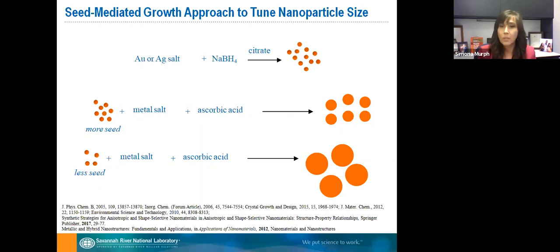And you can see here what I display. They are actually spherical nanoparticles. And you might wonder, why do I have sodium borohydride in the first step, and after that, ascorbic acid? At the beginning, you want strong reducing agents, and you force the creation of these very small nanoparticles, the seed nanoparticles. After that, you need a milder reducing agent to make sure that you don't create more nucleation centers, but you actually want to grow the spherical nanoparticles into larger particles.